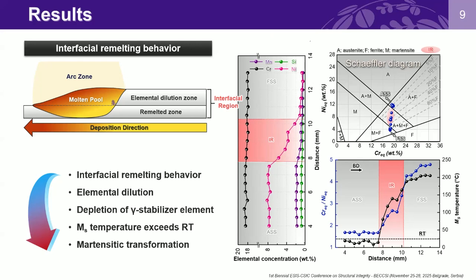The coordinate of the interfacial region is pinpointed within the austenite plus martensite plus ferrite phase area, which coincides with the experimentally observed results.